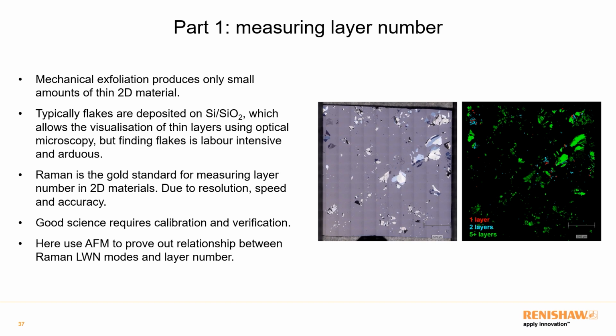Alternate methods for measuring layer number include Raman spectroscopy. This is deemed the gold standard, so this is very useful because you can do it to a high spatial resolution, and you can do it with high speed and accuracy. So with something like graphene, the standard technique is you find a flake, you do Raman on the flake, you determine its thickness, job done.